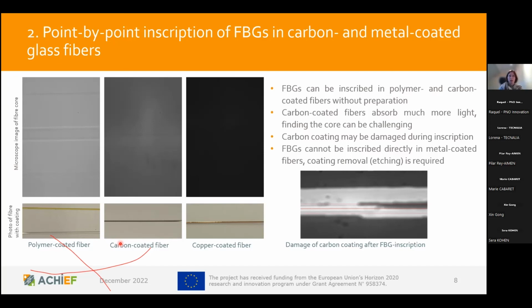So we thought we actually would also test metallic covered fibers here. If we could directly write into these fibers, that would save us a processing step. However, the setup relies on optically detecting the core of the optical fiber. You can see that for the polymer coating, we could nicely see through the fiber. The carbon coating decreases to some extent the amount of light that actually gets shone through.